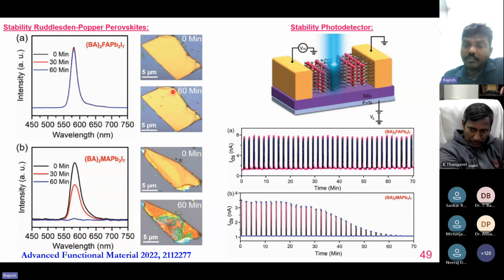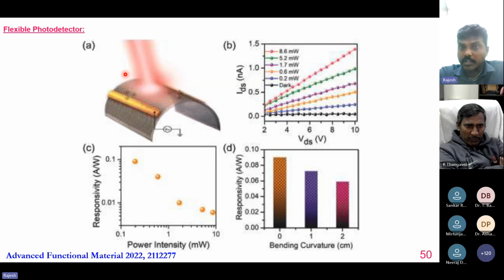And we also demonstrate the same phenomenon in the device part. As you can clearly see, when we switch the light on and off, the on-off current is increasing constantly without any degradation. But in the case of the methylammonium based device, when it reaches 20 minutes it starts to degrade, and in almost 1 hour it's completely degraded, which proves our FA based material is a strong candidate for optoelectronic applications. And again, we showed this material can be used as a flexible photodetector, and we obtained a very high responsivity on our flexible device.